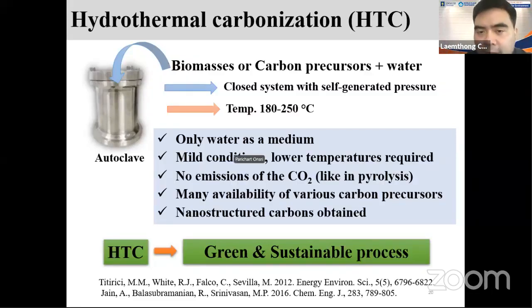There's the so-called autoclave, and you put the water in. When you set the temperature at around 180 up to 250, if you see here, it's quite a low temperature compared to the others. So you have really mild conditions compared to the normal activation process. You use only water as a medium, you use mild conditions, and you can lower the temperature.